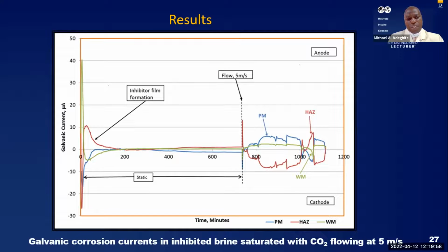So the test being conducted, we can also see the reversal of the corrosion current here, the galvanic current. It also establishes that the inhibitor is not consistent. So this is with a typical chemical inhibitor, and we can see the current reversal. The current reversal shows that there is a buildup of protective layer and then a breaking of the same. And when we have the breaking of the protective layer, the corrosion rate spikes. And of course, it shows that the inhibitor is not as reliable as we are taught it will be.